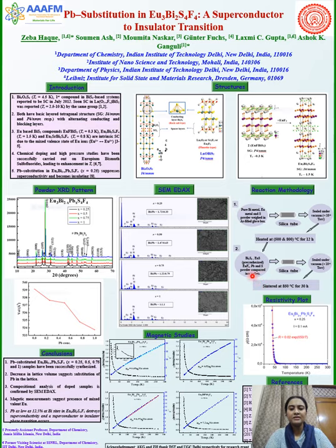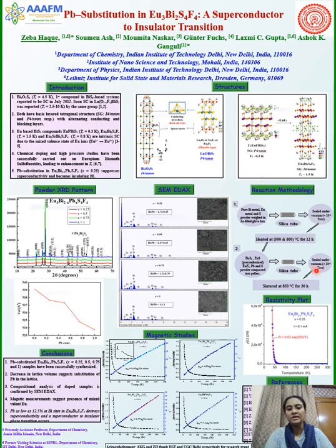All reactants were mixed, ground well, and compacted into circular pellets. These circular pellets were vacuum sealed in quartz tubes, which were then baked at 800 degrees centigrade for 30 hours.